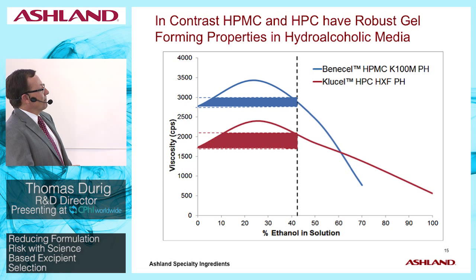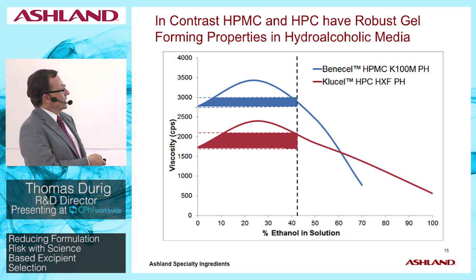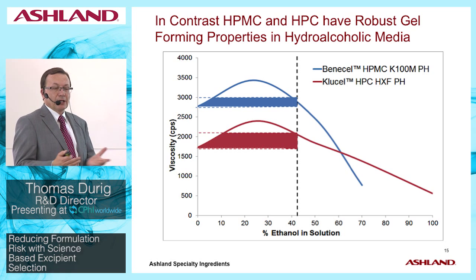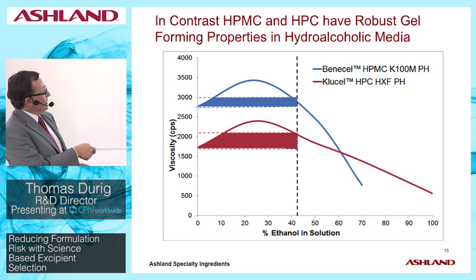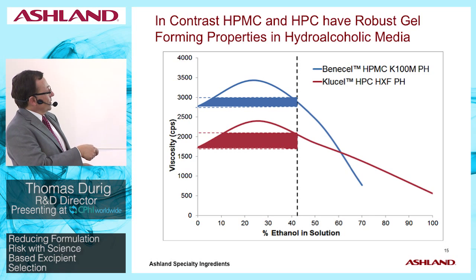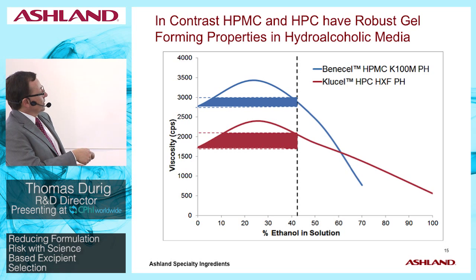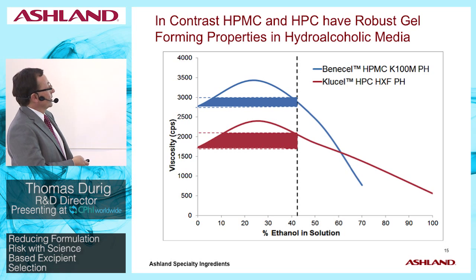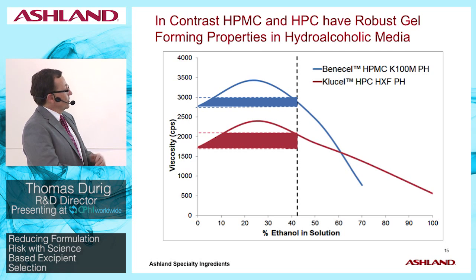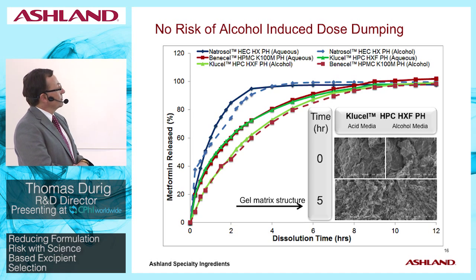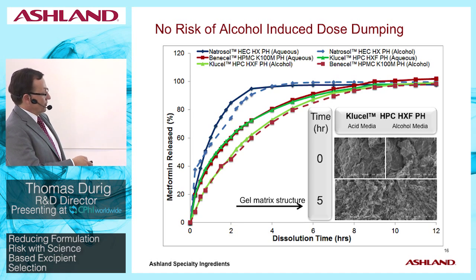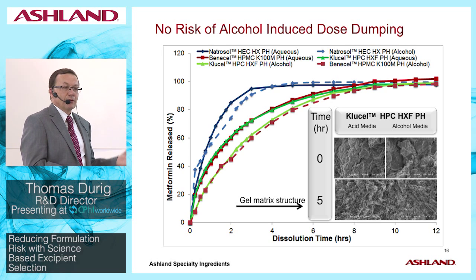if we look at some of the other modified release, controlled release polymers, such as HPMC and HPC, which have a better balance between hydrophobic and hydrophilic properties, we can actually see that in this case, these polymers not only form gels, but even slightly increase the viscosity as one adds ethanol to an aqueous solution. So in fact, up to 40% ethanol in an aqueous solution, these are very robust gel-forming polymers. And so therefore, not surprisingly, when making dosage forms with these matrix polymers, such as HPMC or even HEC as well as HPC, there's really no effect in terms of dose dumping as we increase the alcohol content of the dissolution medium from 0 to 40%.